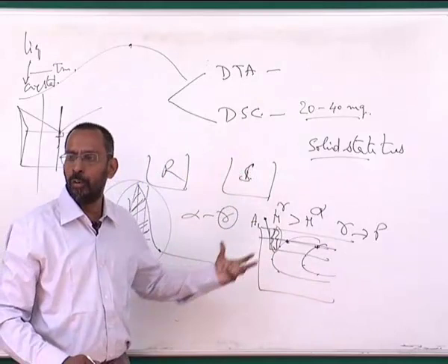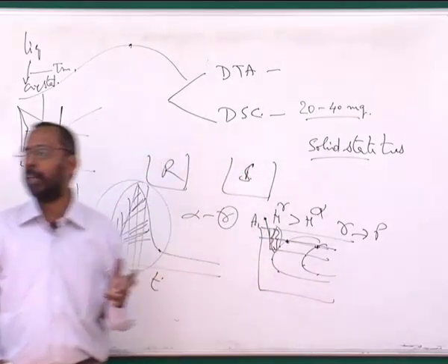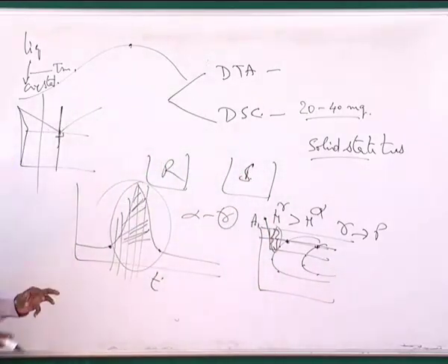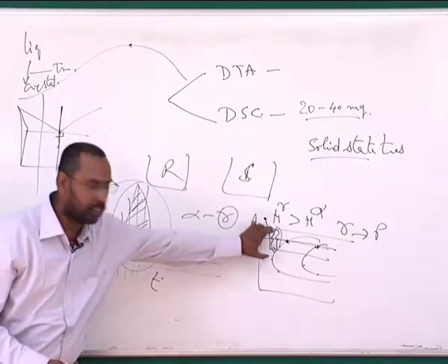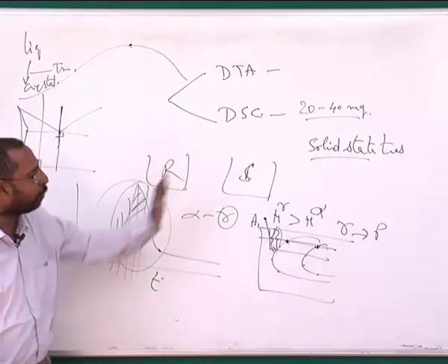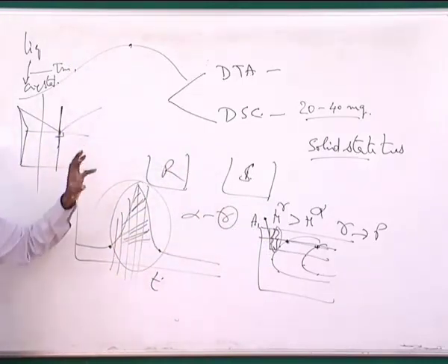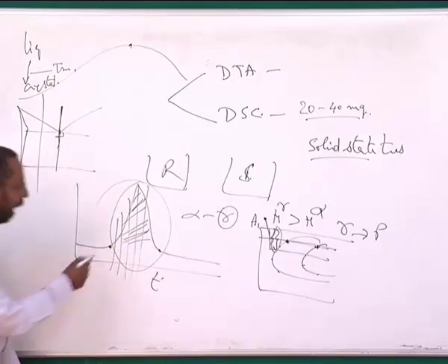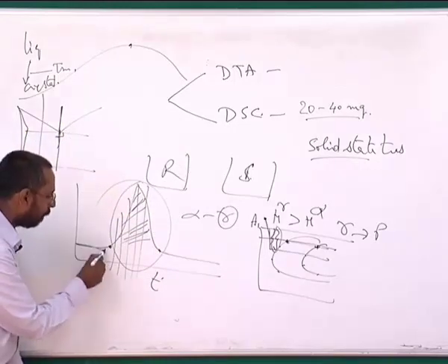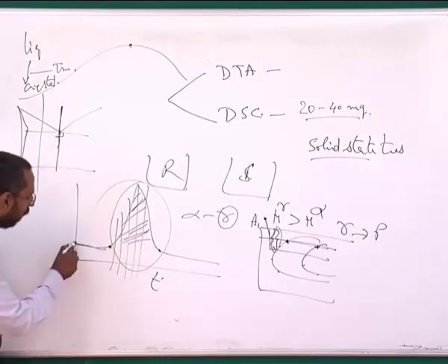If something has already nucleated, all my kinetics that I am getting are going to be wrong, because already some nucleation has taken place. Similarly, when I am trying to do the reverse process, I should make sure that no gamma has formed during heating, so that the alpha remains as alpha until you reach this particular temperature and start holding. And what is this period?